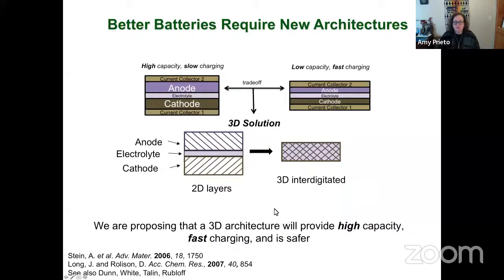So why would you want a better architecture or a new architecture for a battery? I mentioned previously, I think of these as 2D batteries. And the challenge really is if you want high capacity, typically what people do is make the anode and cathode layers quite thick. And that results in very long diffusion paths, which you observe by having a battery that is very slow to charge and discharge. High power batteries are typically made by making very thin anode and cathode laminates and then stacking many of them. The challenge there then is the trade-off is low capacity, but you get very fast charging.